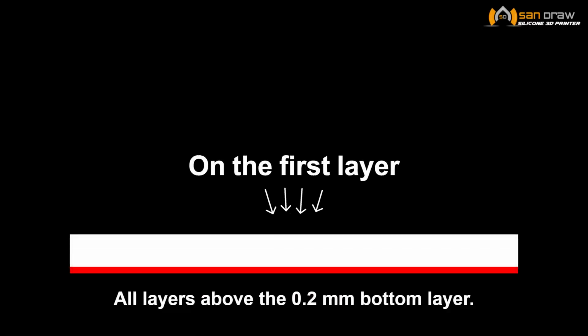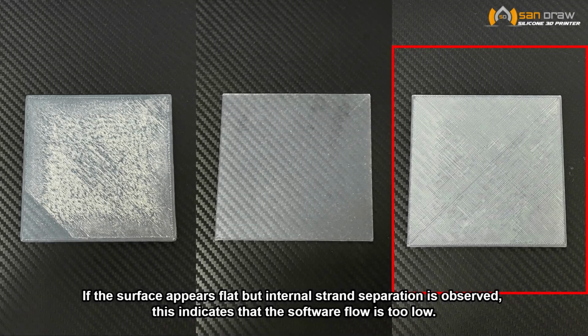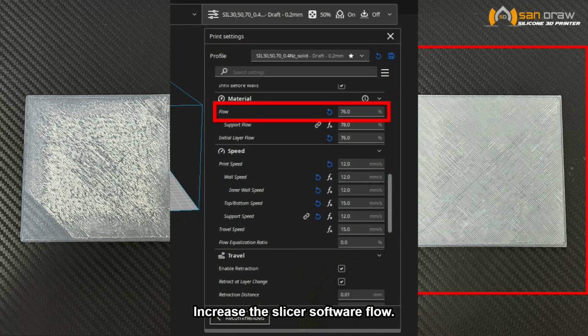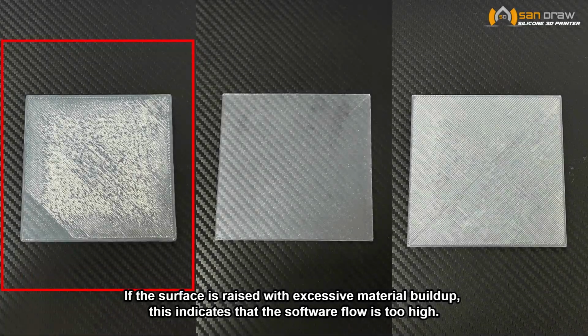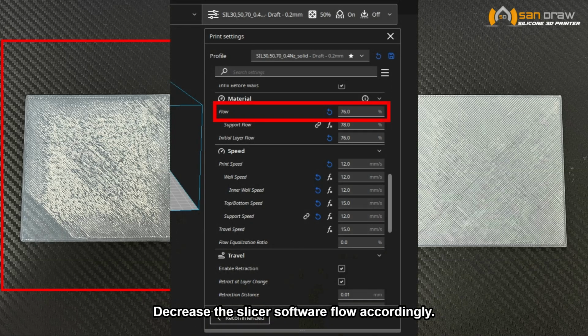For the subsequent layers, if the surface appears flat but internal strand separation is observed, this indicates that the software flow is too low. Increase the slicer software flow. If the surface is raised with excessive material buildup, this indicates that the software flow is too high. Decrease the slicer software flow accordingly.